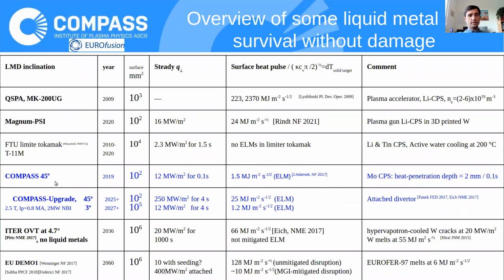The experiments I will show you now were done on COMPASS, where 1.5 years ago we exposed a pretty small target at a very large incidence angle to relevant heat fluxes, 12 megawatts per square meter, with pretty small ELMs, because our ELMs are not any bigger. And on COMPASS Upgrade, we are going to do the same thing, and that's why we can achieve extremely high heat fluxes, which are pretty close to what is one day expected on DEMO in an attached divertor plasma, including the ELMs. So this is just a small target, and then we plan in the farther future, since 2027, to have a much larger area, a full coverage liquid metal divertor, so the incidence angle would be small and the heat flux also relatively smaller.